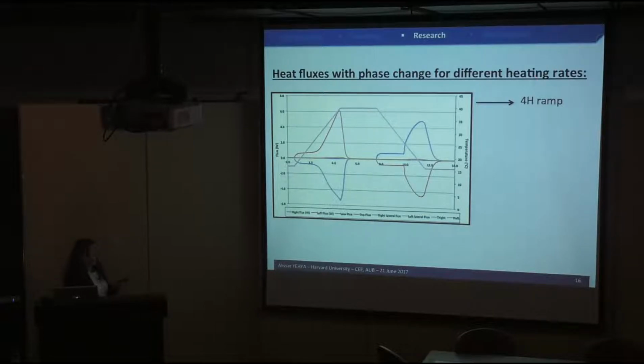within 4 hours. This is the curve, the heat flux for the melting side, and this is for the solidification side. The first thing we see is that they are not symmetrical. So the solidification and the melting phenomena are different. They have different kinetics. Here is the sensible heat, and then we have a gradual melting, while in the solidification we can see that it's more of an immediate solidification.